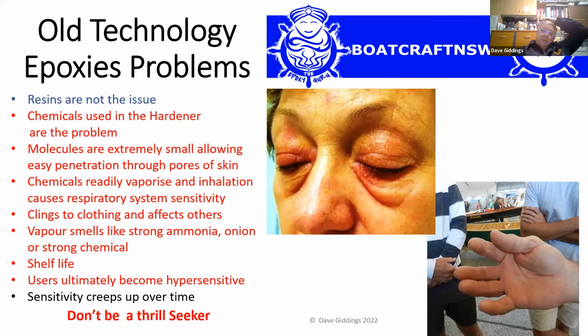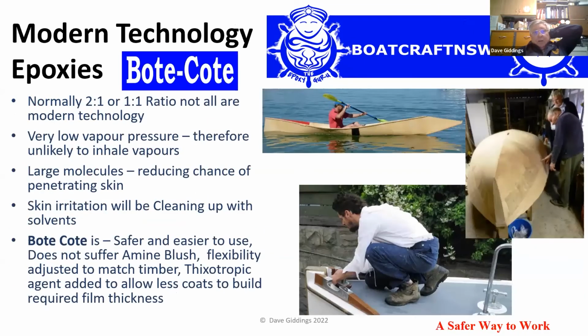All I can say is if you're using old technology epoxies, you're a thrill seeker. Modern technology epoxies, they're normally a 2-to-1 or a 1-to-1 ratio. Not always, but usually they are. They've got a very low vapor pressure, so it doesn't readily vaporize. You could use Bote-Cote in the office where I am now, except I've got a heater going, and it won't vaporize. It's got to get around 50, 60 degrees C before it starts to vaporize. The molecules are a lot larger than the pores of your skin, so it won't go in through your skin.